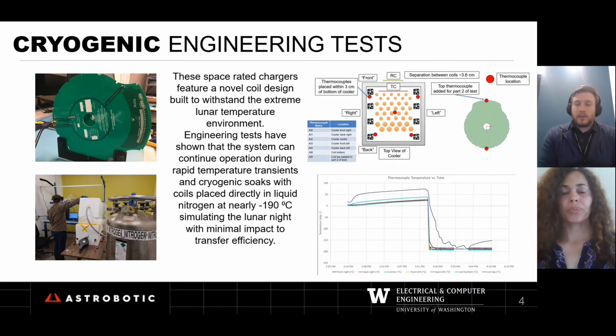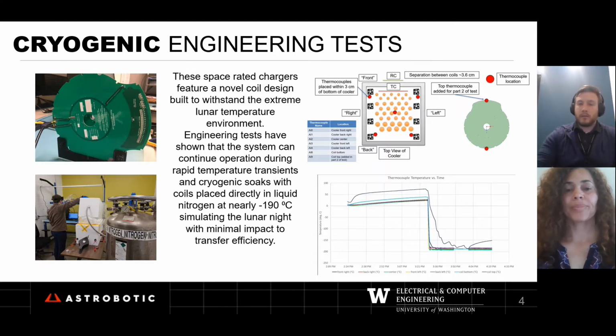You can see on the right here that transient happened very rapidly, and during which time power was transferred, and we noted no degradation of transfer efficiencies, and inspections of the coils post-test yielded no reasonable impact to material properties or any other characteristics. Shanti?